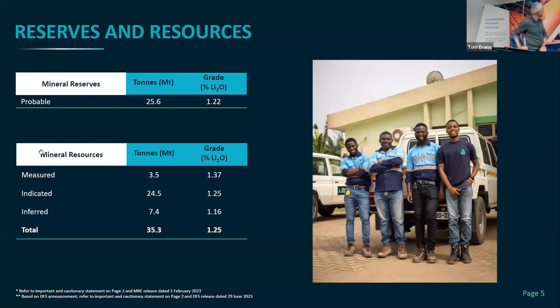So the total resource is now sitting at 35.3 million tonnes at 1.25% lithium oxide. And you can see a large portion of that is in the high confidence category of measured and indicated. From a mining point of view, a large portion of that converts to reserve. So it's got good continuity and good modifying factors, and that's all down to the processability, proximity to infrastructure, and available workforce. So, good resource to reserve conversion.